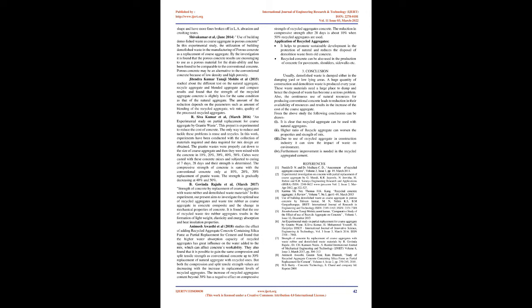In this experimental study, the utilization of building demolished waste in the manufacturing of porous concrete as a replacement of coarse aggregate. By the investigation, it is found that the porous concrete results are encouraging to use as a porous material for the drainability and has been found to be comparable to the conventional concrete. Porous concrete may be an alternative to the conventional concrete because of low density and high porosity.